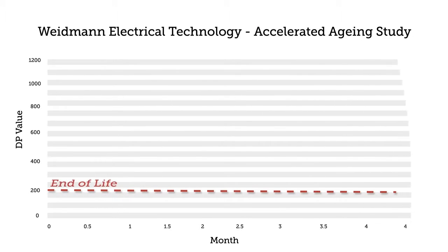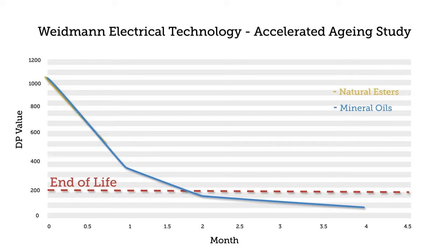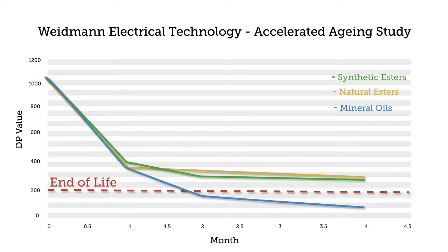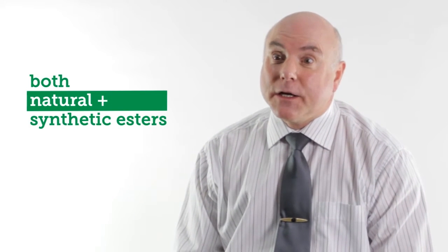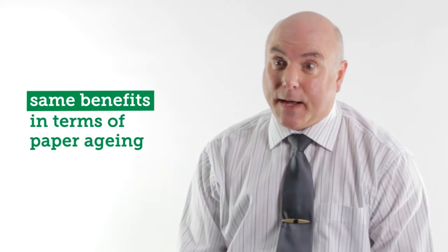One accelerated aging study conducted by paper experts Weidmann Electrical Technology showed the benefits of using ester fluids. Cellulose pressboard samples immersed in mineral oils reached the end of their life after 2 months when aged at 150 degrees centigrade. In comparison, at the same temperature, similar pressboard samples immersed in natural and synthetic esters retained a DP value of over 200 after 4 months. Crucially, the results from the Weidmann study show that both natural and synthetic esters confer the same benefits in terms of paper aging.